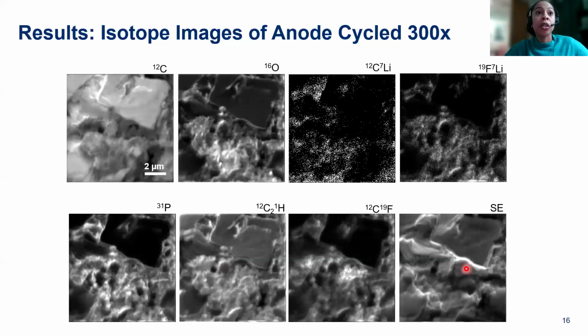And then we can also look at the isotope images generated for the sample cycled 300 times, which is a much longer aging lifetime. We can see, first of all, that we have a much higher 12C7Li signal distributed all over the sample. But again, we don't see very much 12C19F on the basal plane on the surface, nor 31P on the surface. But we have carbonaceous species again all over the sample.